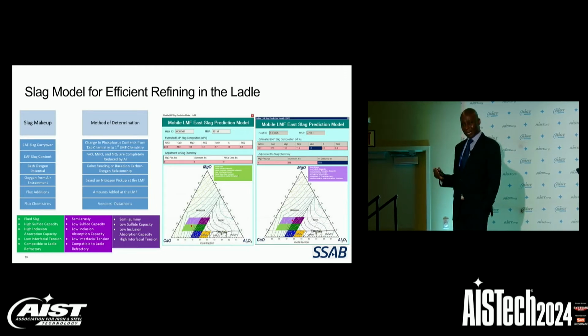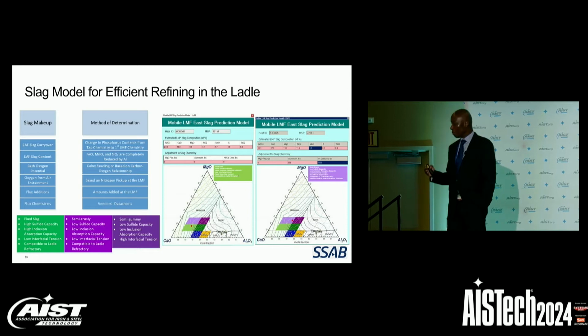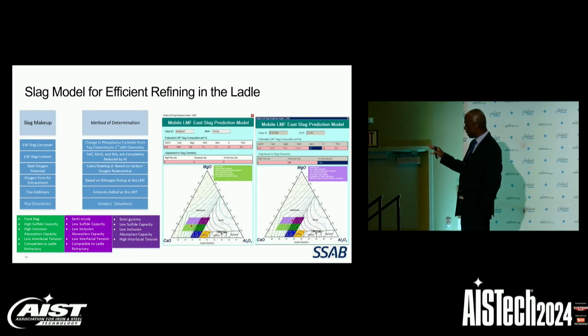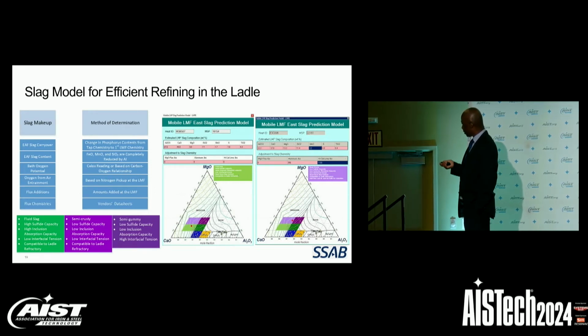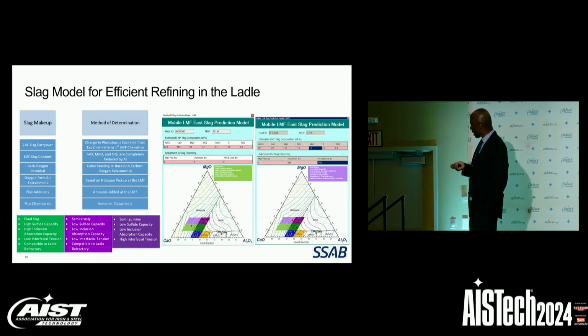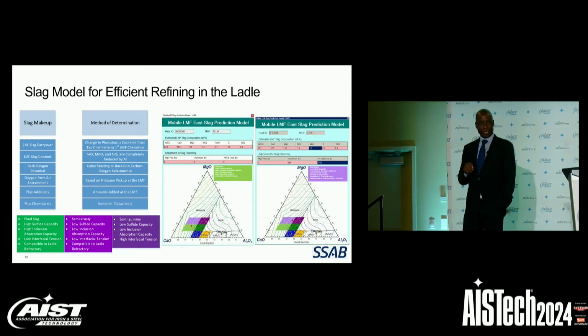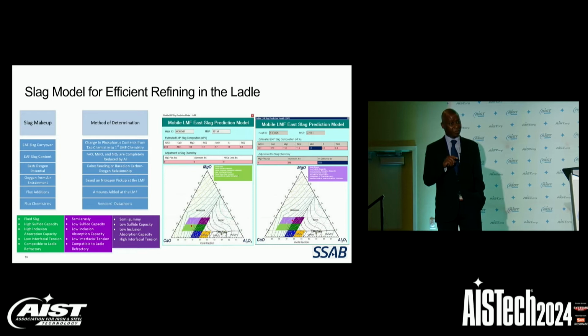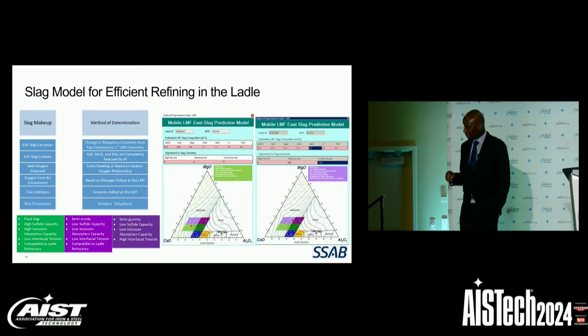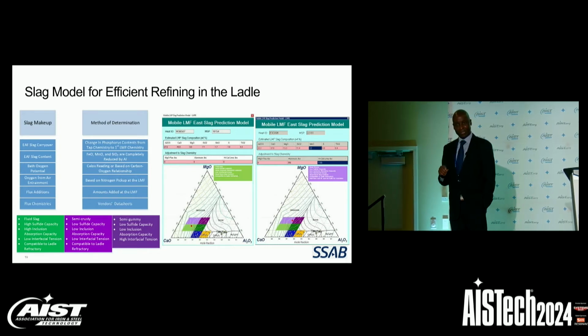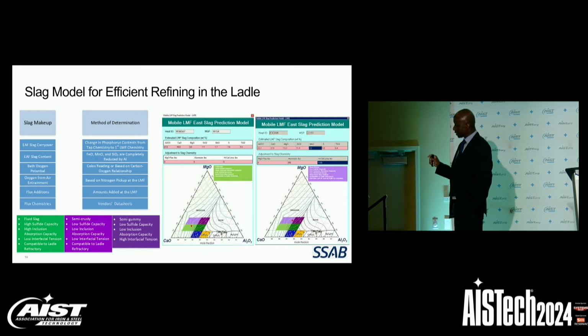And by normalizing the concentration of the slags, we are able to represent them in the ternary plot of calcium oxide, MgO, and alumina. So the operators can see the condition of their slag during refining in the ladle. Now, what you are seeing on the right here is the predicted slag condition of the heat that I reported on the previous slide that experienced difficulty desulfurizing. Our model was able to determine that the slag is semi-crusty and has low sulfide capacity.